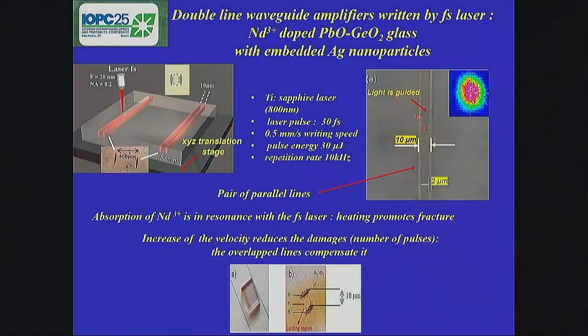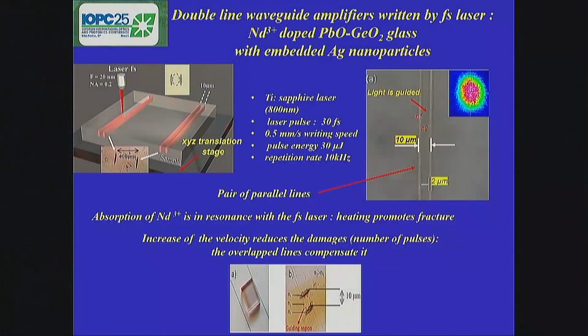We increased the velocity with respect to the other experiment, and in this case, we reduced the damage because the number of pulses was reduced, but we had another problem. The contrast between the refractive index was not enough to provide an ideal confinement of the light. And we overcame this problem by using several overlapped lines. In fact, our waveguides are formed by pairs of parallel lines separated by 10 micrometers where light is guided. And now each of these lines is formed by several overlapped lines, and we chose different numbers, 4 and 8, and they were determined empirically.